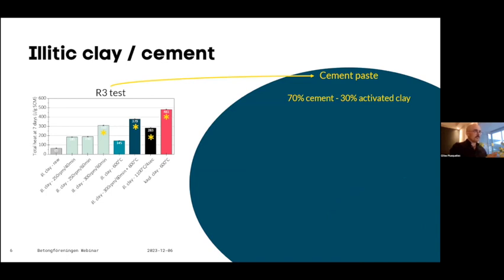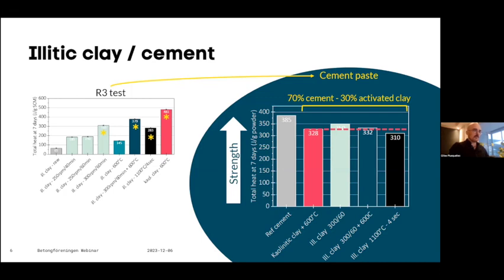at the cement paste level. So we took a CEM I and replaced 30% of it with activated clays, the ones that have the yellow star here. And we looked at the hydration of the cement paste. Here's the result for the isothermal calorimetry, and it's the total heat after 7 days of hydration at 20 degrees. And we know that this value is directly linked to the strength of the product.